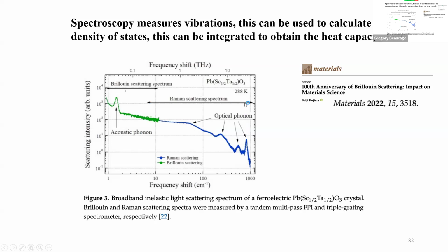So IR and Raman would give you these. IR gives you the ones where, if you have a salt and it's polar, the polar bonds light up in IR, and then Raman gives you the things where you have electron mobility, like conjugated double bonds in graphene or buckyballs or nanotubes. If you're going to look at nanotubes, you do a lot of Raman spectroscopy. From the absorption band, you can tell there's a D band and a G band or something, and you can tell the difference.